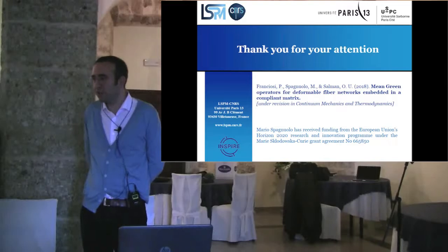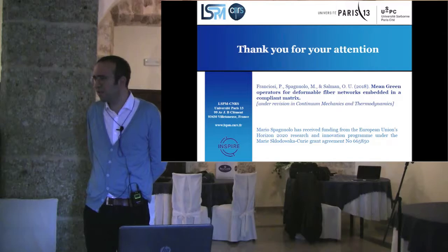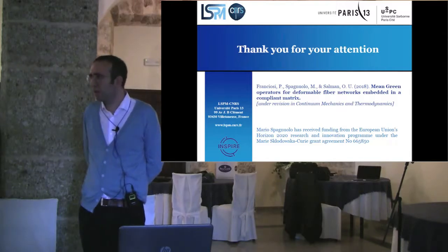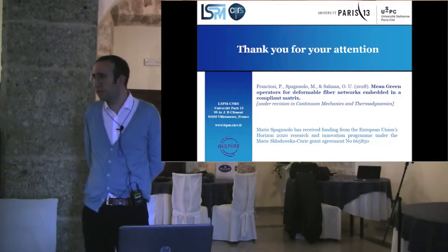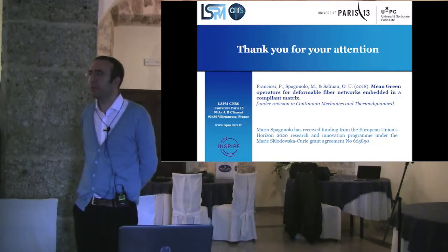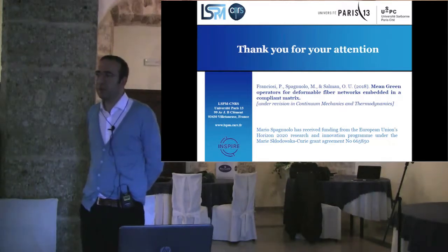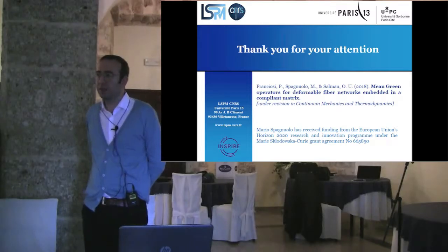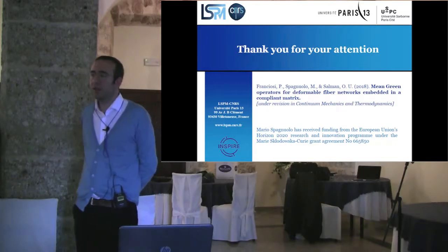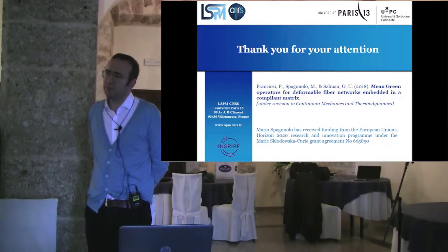Yes, I think it's the same approach. It was started by Eshelby before, and after that came the effective field. You consider every inclusion as an isolated one, in the effective field created by all the other inclusions. There are two Green functions, one for the inclusion and one for the symmetry of the distribution of the inclusions.